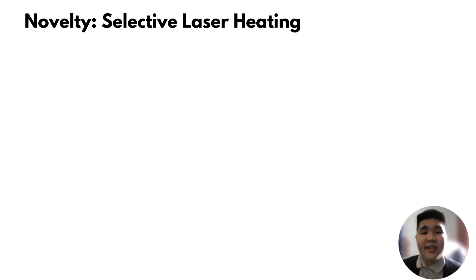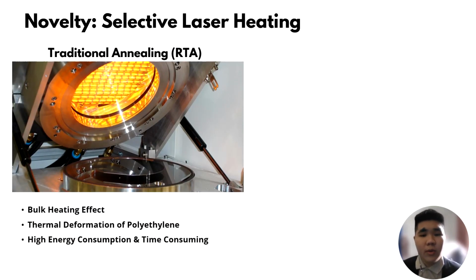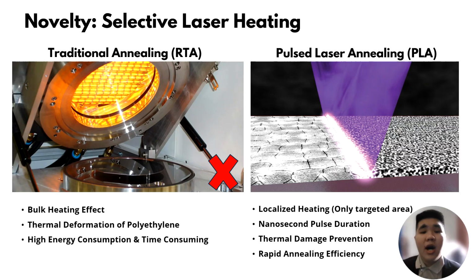The novelty of this project lies in the heating mechanism. Traditional thermal annealing uses global heating, which wastes energy and destroys flexible plastic. In contrast, our pulse laser annealing is selective. The laser energy is absorbed only by the silver layer, leaving the PET substrate cool and intact. This allows us to bring high-performance metal to low-cost plastic.